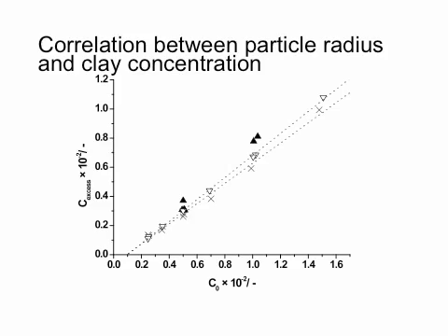The good news about this approach is that before we do the experiment, we roughly know how big the particle size is going to be. That's very useful. Because if you say, I want to make these particles and I want them to be 500 nanometer, you just plot it on this line and say, okay, you need to use so much clay. And then we know exactly how big the size is going to be. So it's very useful.